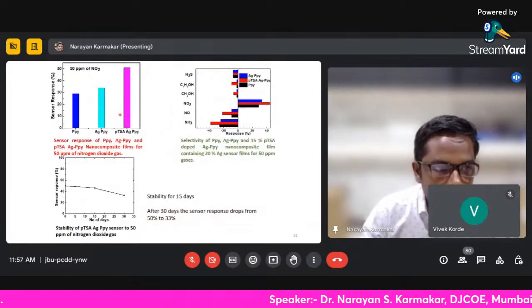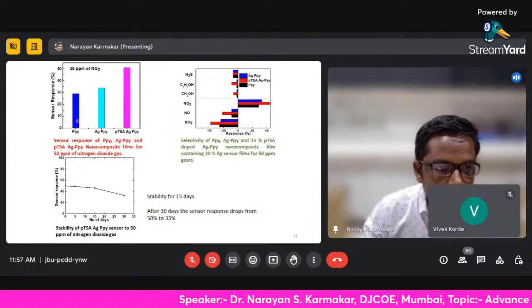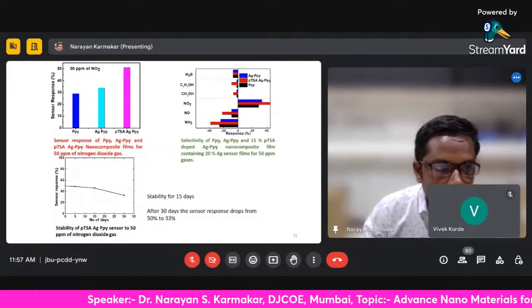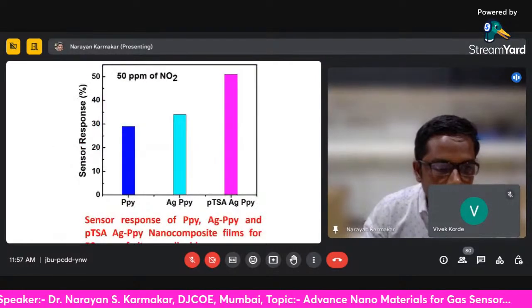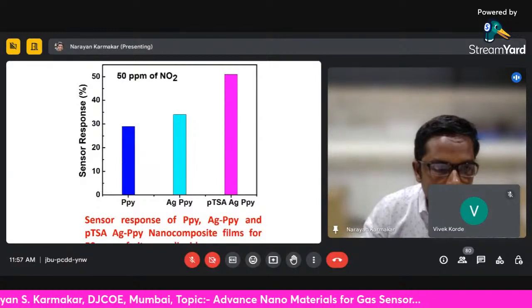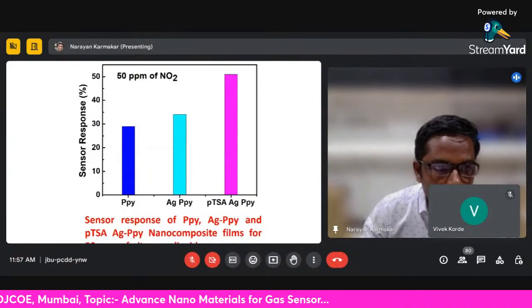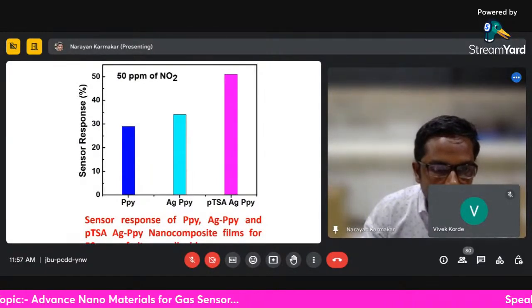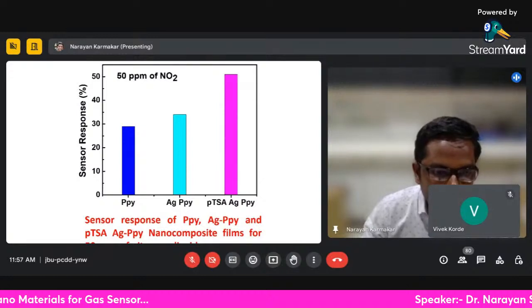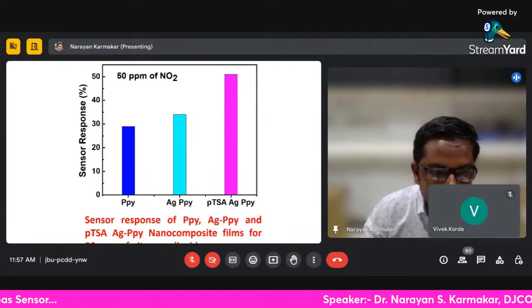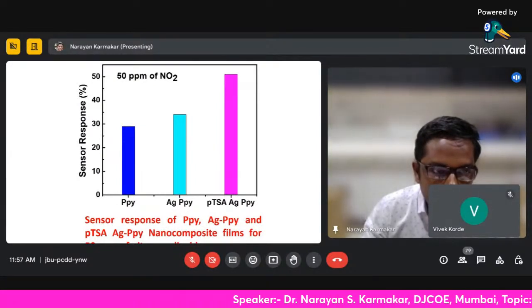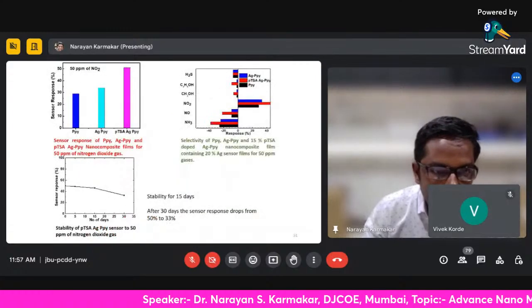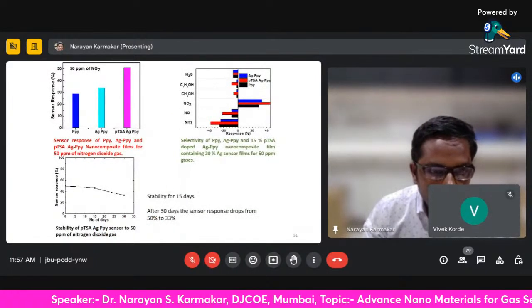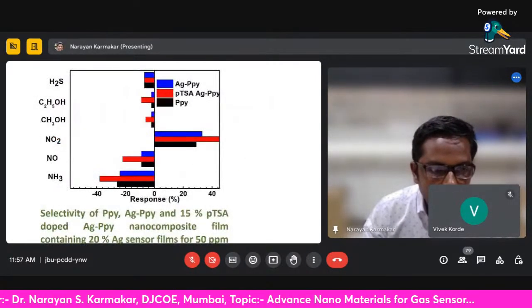Also, here is a summary of the sensor response: for PPy, the response is about 30%. When doped as AgPPy, the response increases to about 35%. And when doped with PTSA, as PTSA-AgPPy, the response increases to 50%.